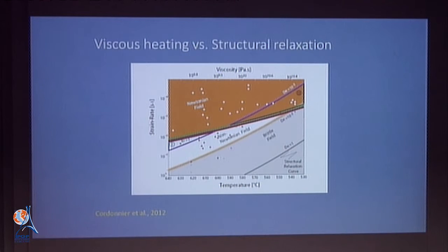And what we discovered is that there are 2 different boundaries which cross each other, one of which implies that first you will get viscous heating, and the other of which implies first you will get structural collapse of the liquid. And these 2 results could not be more different, because in one case, viscous heating, you push yourself away from fragmentation. You push yourself away from the catastrophic event of destroying the rock, because the temperature increase decreases the viscosity of the liquid. And so you basically avoid the catastrophe. And in the other case, you're observing the catastrophe through the structural collapse of the liquid.